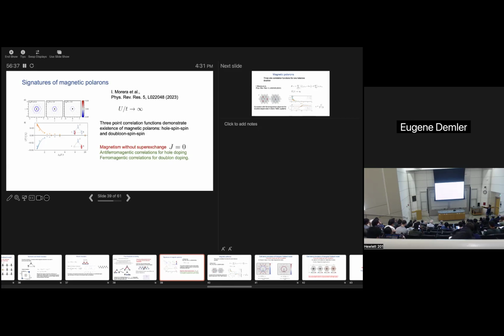So it's not such an unphysical regime to analyze. So clearly, in this case, when U is so large, our superexchange, which is T squared over U, is essentially zero. So there is no superexchange mechanism to speak of as we're used to. However, we still have this kinetic mechanism. So we know that the hole will favor an antiferromagnetic spin configuration around itself. But in the case of the doublon, we don't have to do the particle-hole transformation. Actually, we will favor a ferromagnetic configuration.